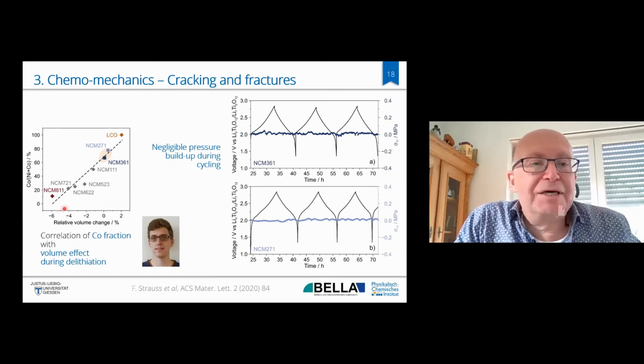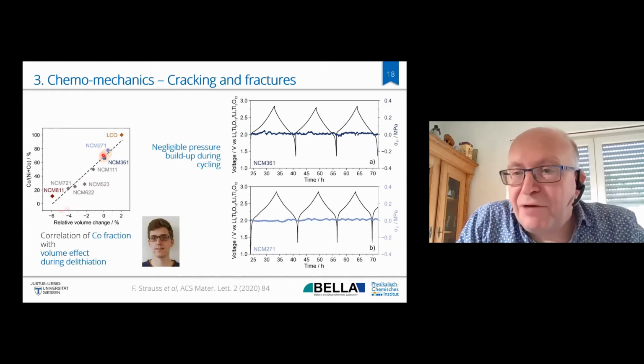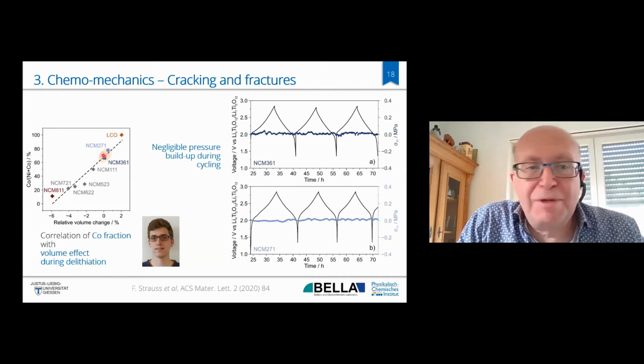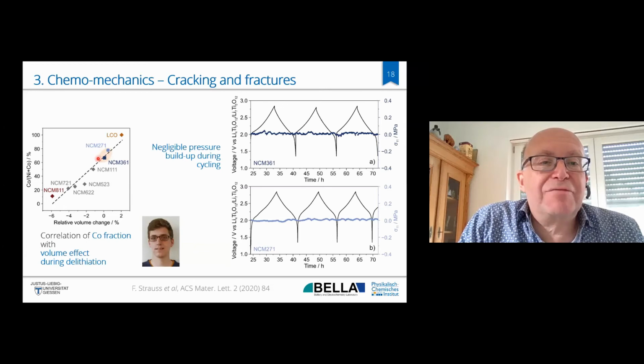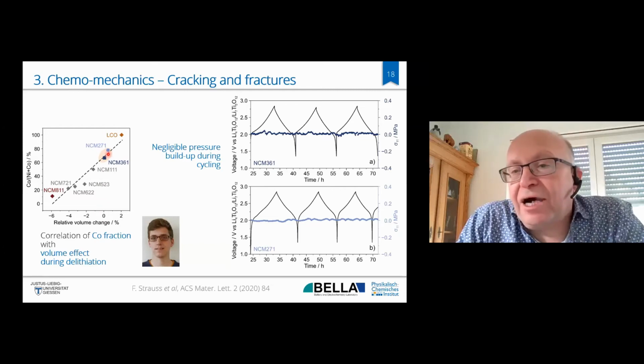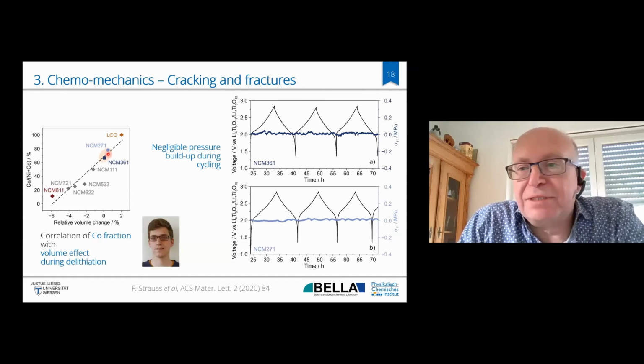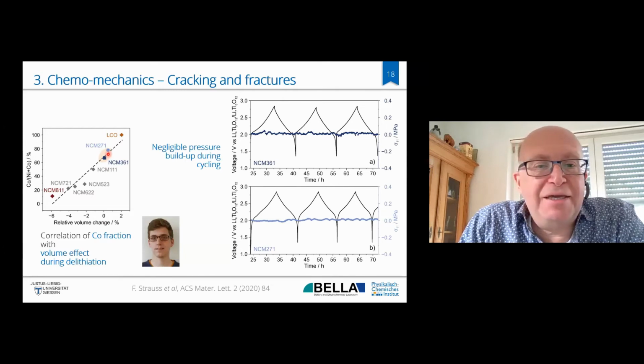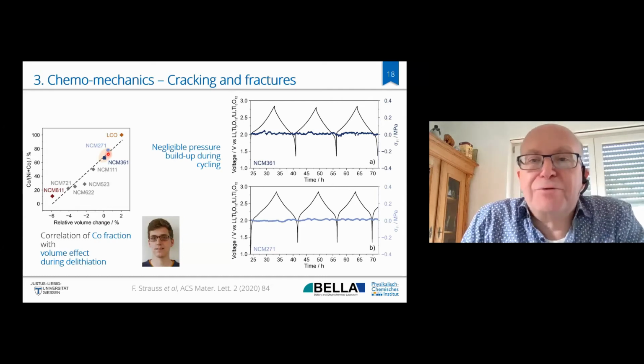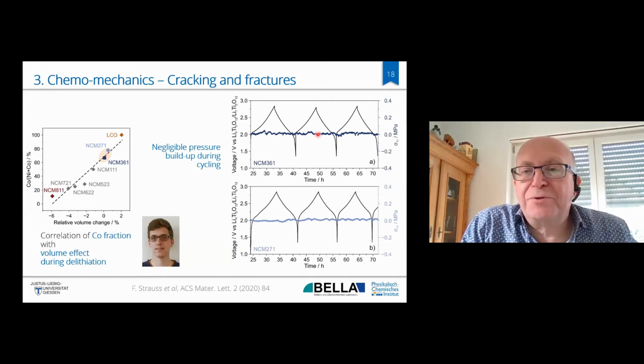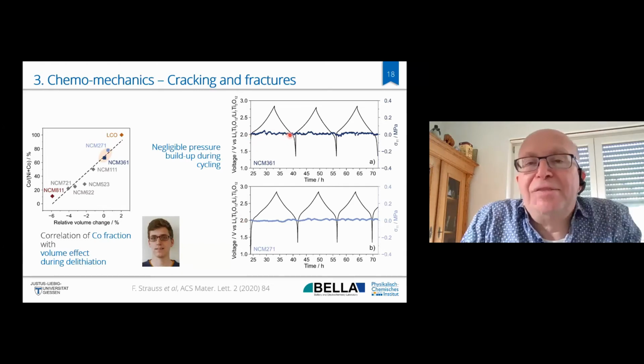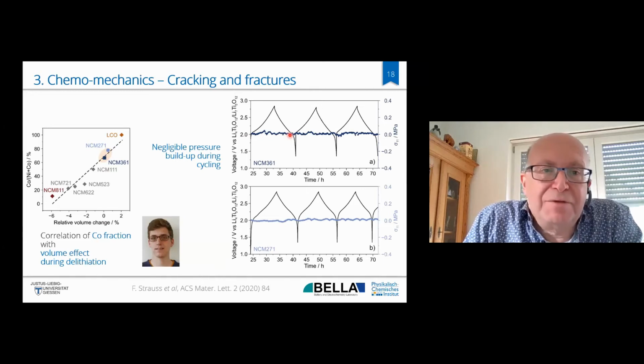So Florian from the Bella Lab showed that if you go within the NCM family to NCM 271 and NCM 361, these materials, unfortunately being, I would say, high cobalt materials and not high nickel materials, with these fractions of nickel, cobalt, and manganese show virtually zero relative volume change. So I think volume neutral cathode materials can be developed. Of course, the volume change is not isotropic, and the a and c axes deform differently. So there is still local strain, but nevertheless, during cycling, we see that there is virtually no volume change, no pressure coming up in these cells, which is an improvement, however, at the cost of a higher cobalt content.